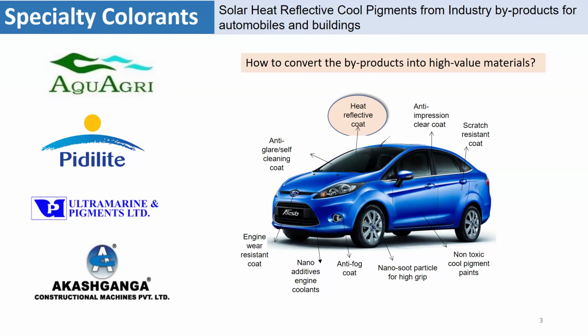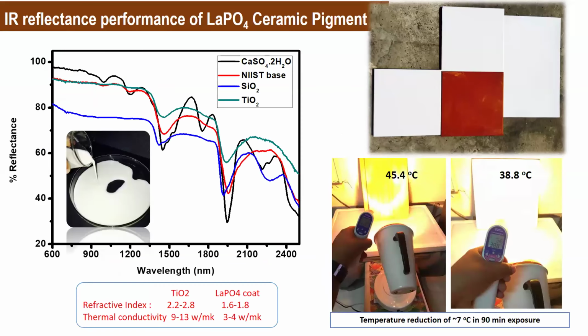And next slide is, for example, I told you that there is a material called lanthanum phosphate, and we are very closely working with lanthanum phosphate because IREL Kollam, they have lanthanum oxide and cerium oxide, and they also have praseodymium oxide and zirconium oxide, yttrium oxide, and we are taking only lanthanum oxide and cerium oxide and converting that into lanthanum phosphate and validating the lanthanum phosphate for IR reflectance.